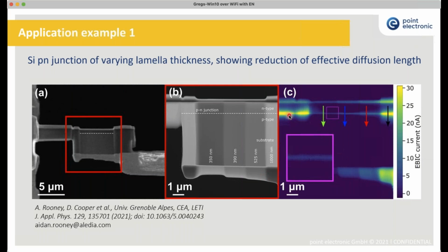And in addition to it, we also see a line where the junction is. And this is where the electric field is. So we have a direct image of the field. And we can see that the intensity of this line depends on the thickness. And that makes sense. The thicker the sample, the more energy we lose, the more electron hole pairs we induce, therefore the higher the current that we pick up.